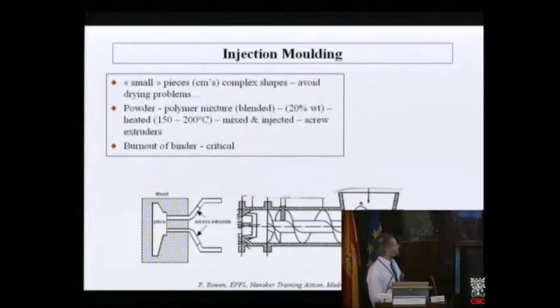You have a powder polymer mixture. Normally it's heated up to 150, 200 degrees centigrade. You inject this very viscous medium using a screw extruder or a piston. Then we have to burn out the binder. If you have this huge quantity of polymer, which fills most of the porosity in our ceramic, we have to burn it out. But also, if you're doing big pieces, for a typical precision piece, complex shape, if you can press it, press it.